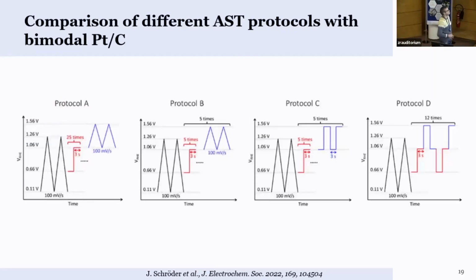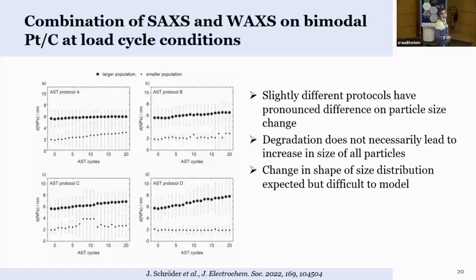And then of course you can look at different protocols that you can come up with to study these systems, and you see that the combination of these protocols is having a very large effect on how these mixed catalysts react to it. And one thing that is also important is that the small population size not necessarily changes. So you can have a large degradation where the average size of the small particles actually stays more or less the same, but still the large particles grow a lot. So it's very important not only to have the information of the average size, but also to have the size distribution and to have a value for the absolute number of particles established in such a system.